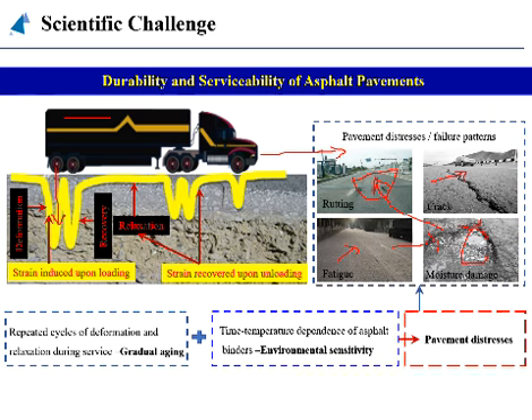So these are basically the general failure modes that occur in the pavement structure because of the environmental conditions and the traffic loading. This is how relaxation, meaning during loading and unloading, leads to gradual aging of the pavement. These are the environmental changes because of changes in temperature, and how they collectively lead to distress in the pavement structures. So if you want to do some research, conduct a study, whether practical or in the laboratory, we need to know the reasons for, for example, rutting, cracking, fatigue cracking, and moisture damage. And according to these things, we then need to apply the same methodology to assess the behavior of these things.